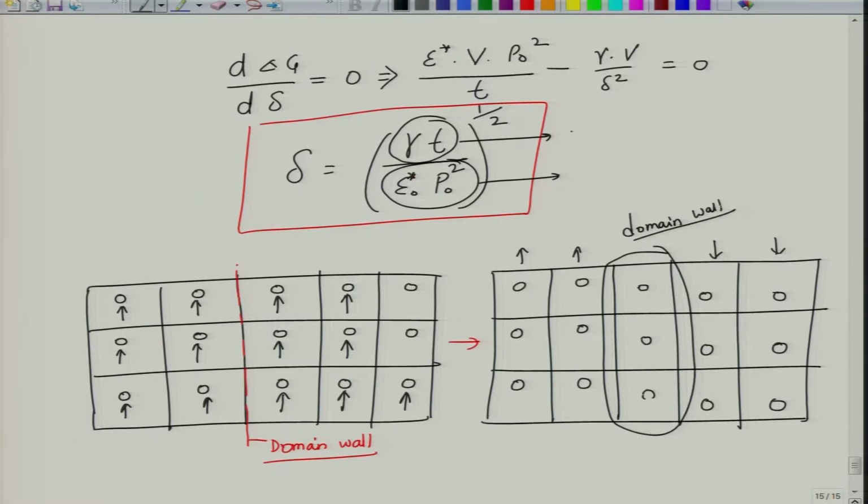the region of disturbance along which the orientation changes, because you have this change in orientation from here to here. These changes will not be abrupt, they will be a little random. So, as a result, each domain wall will also have a domain wall width, which is of the order of a unit cell or so. They are much sharper than magnetic domain walls, but there will be a region in which they have to transition from up to down. So, there could be about a unit cell across which the transition occurs. Okay. So, this is basically a domain wall.